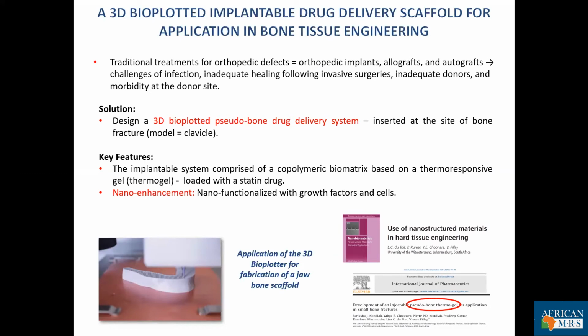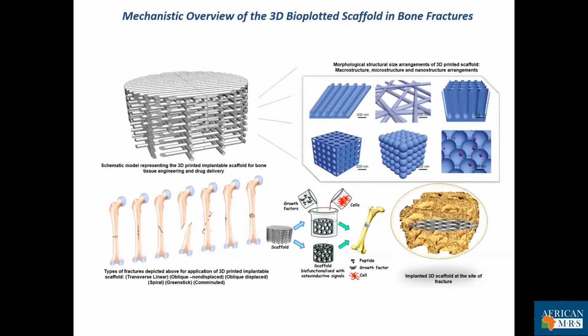What was actually used was the clavicle model. The system was composed of a copolymeric biomatrix, and it was also based on a thermoresponsive gel, which was loaded with a statin drug, which basically stimulates bone regeneration. So what was firstly undertaken was that a 3D model was constructed, and this was then biofunctionalized with various osteoinductive signals, growth factors, and peptides. And this was then implanted at the site of the fracture.